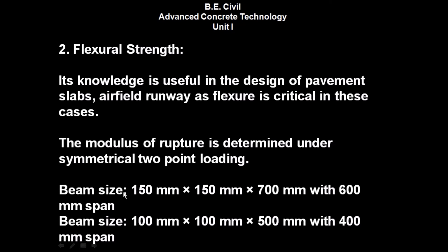The beam size which is used is 150 millimeter by 150 millimeter, and the length will be 700 millimeter with a 600 millimeter span. Another size of beam which can be used for the flexural strength is 100 millimeter by 100 millimeter by 500 millimeter length, and the span will be 400 millimeter to determine the flexural strength.